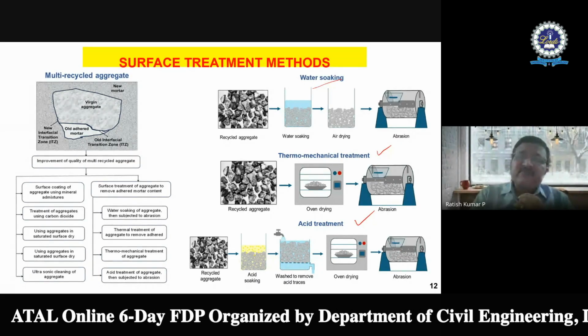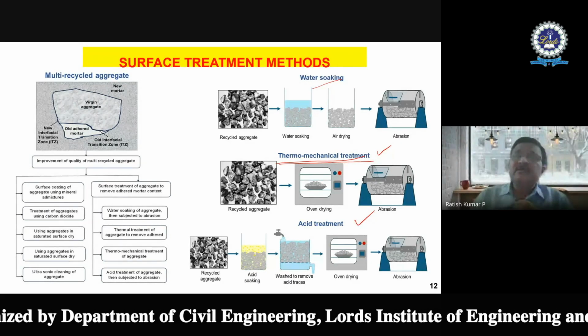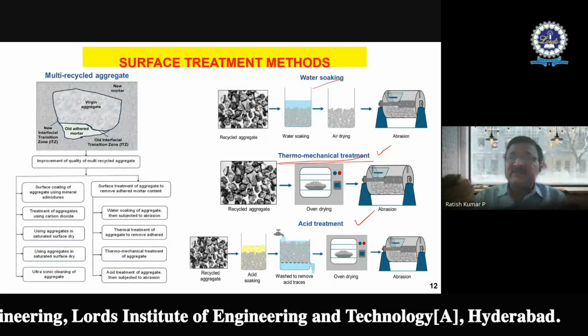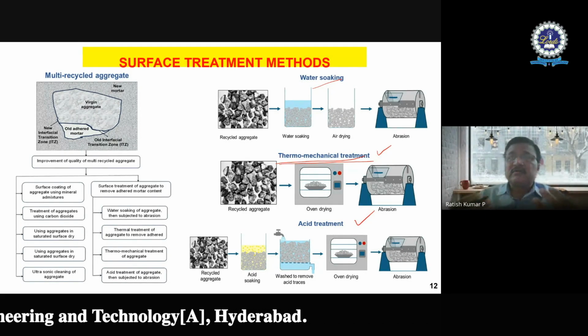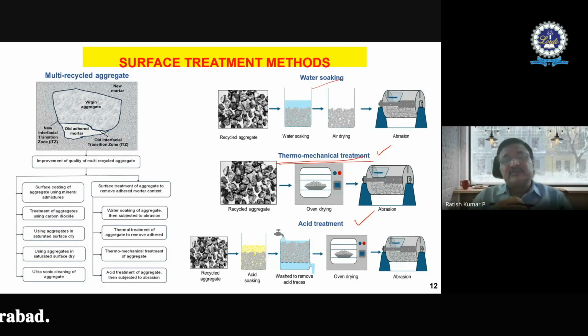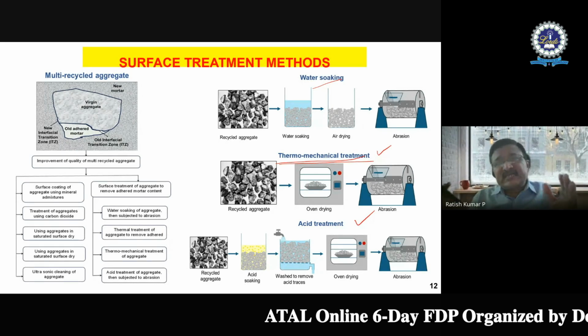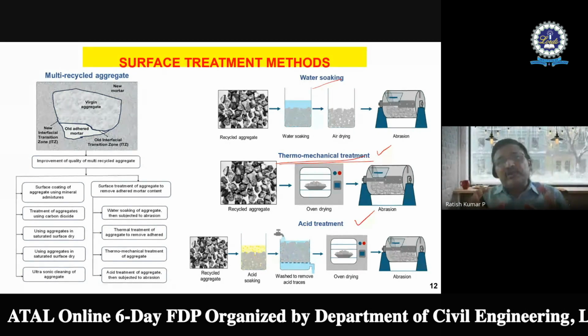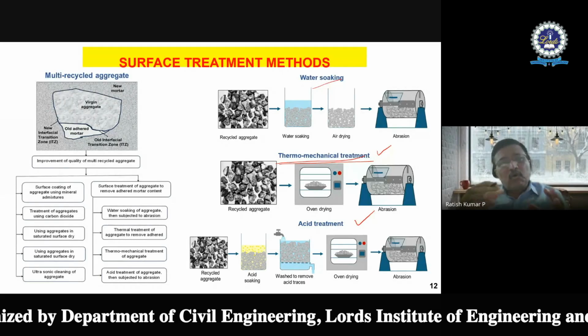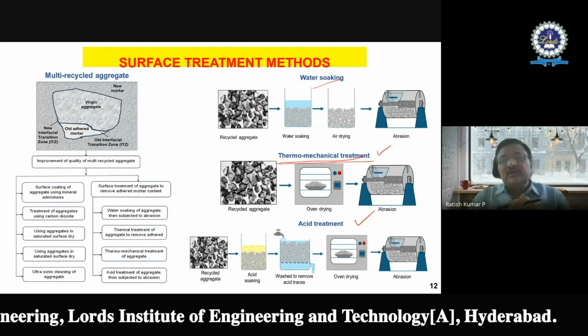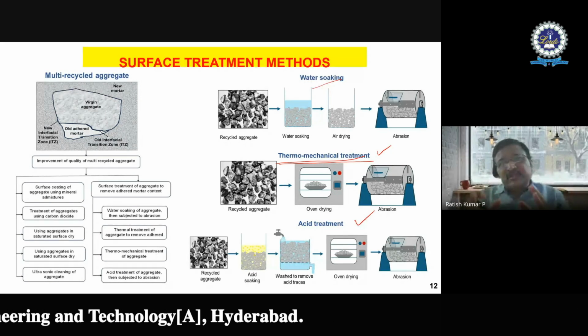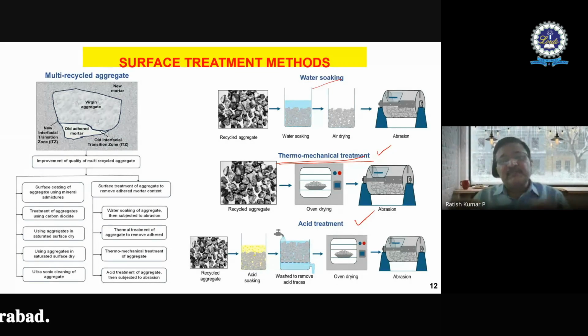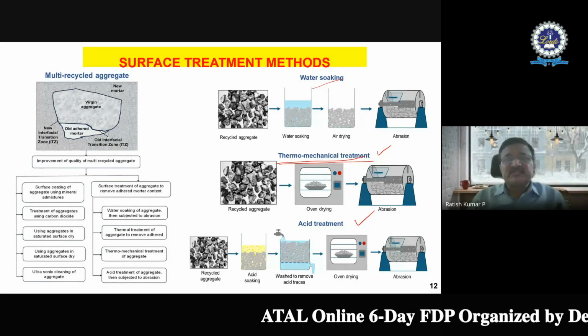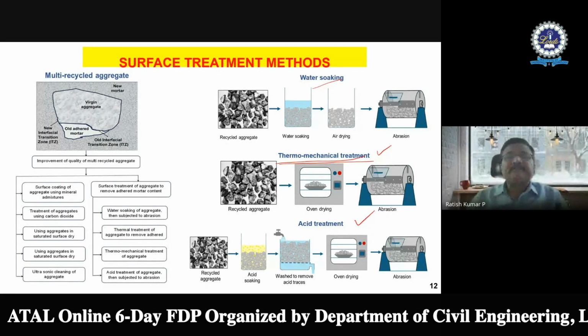I think we can settle with the thermomechanical treatment, which is okay, or we can go for modifying. In case of first generation, for example, we can compensate for the additional water absorption and bring it to a saturated surface dry condition. But you can accept, normally from the literature, that with around 20 to 24, 25, 27% of old mortar adhered onto the aggregate, it is still able to develop around 25 to 30 MPa concrete. So that's not a great problem as long as I'm trying to remove up to 25% or so. That's the point here.